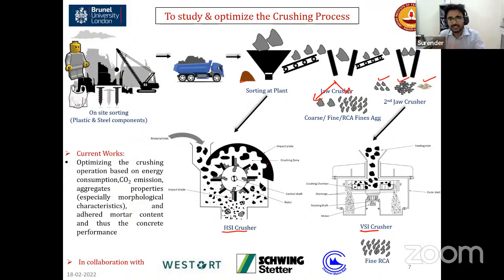So there could be changes in the morphological properties of the aggregates, and then it can have an effect on the aggregate to aggregate interlocking, and also how much it will be affecting the adhered mortar. So all these parameters will be affecting the strength of the concrete. So we are working on this.